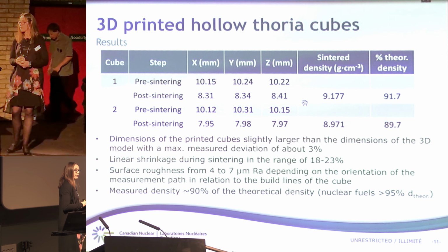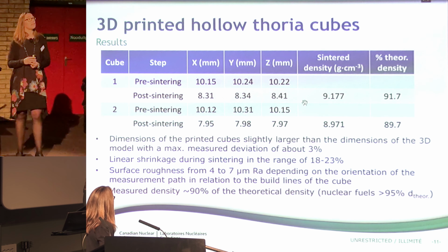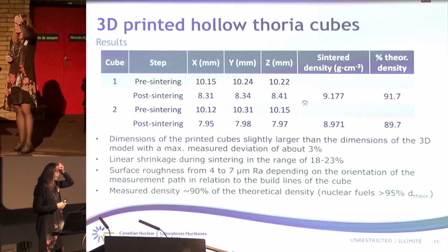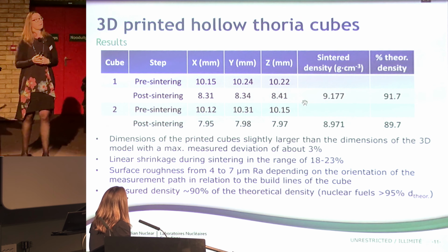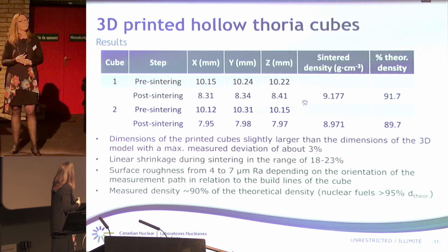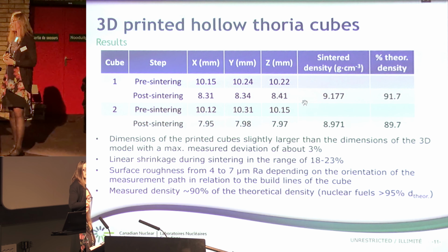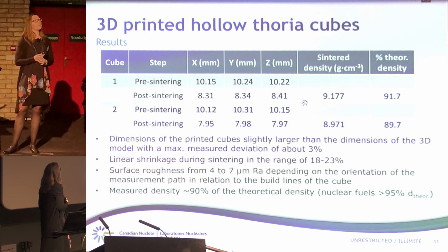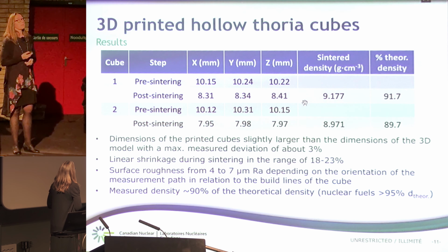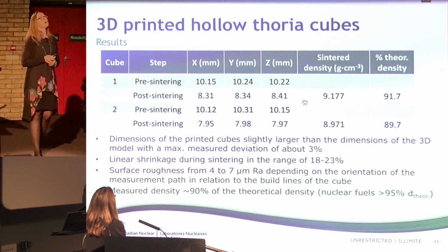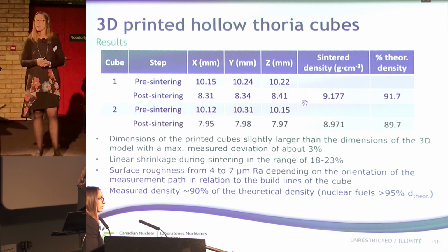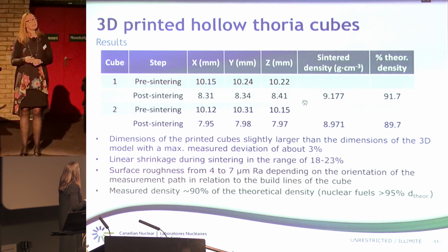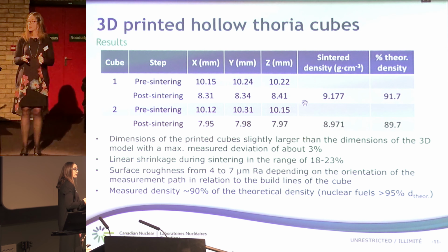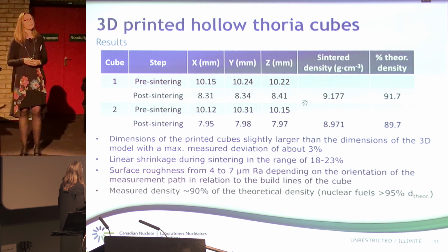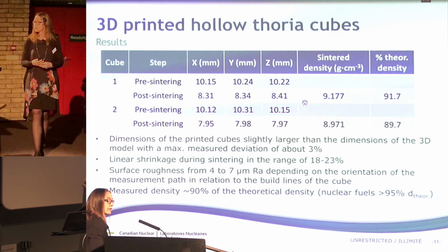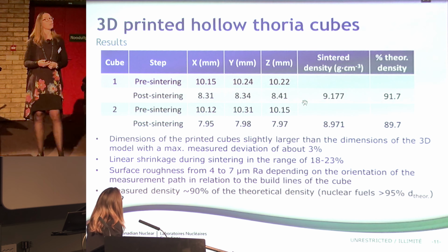The first kind of characterization of those 3D printed parts is given in this table, where we measured quite easily using calipers the different dimensions of those cubes. And as you can see, before sintering, the dimensions of the cubes are slightly larger than the dimensions of the 3D model, with a maximum measured deviation of about 3%. We observe that after sintering, there is quite a large shrinkage, and we also observe slight distortion during these sintering steps. And this linear shrinkage depends on the direction we are looking at, but it's about 18 to 23%, which is the order of magnitude of shrinkage observed when we make UO2 pellets, for example. So that was kind of expected.